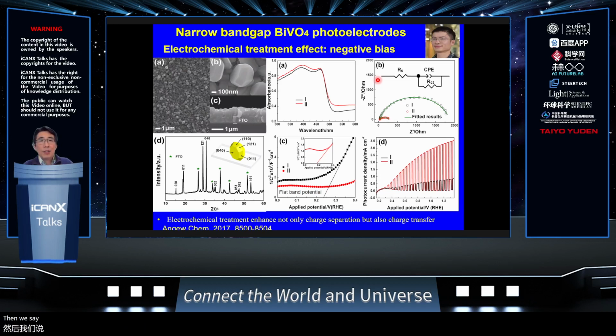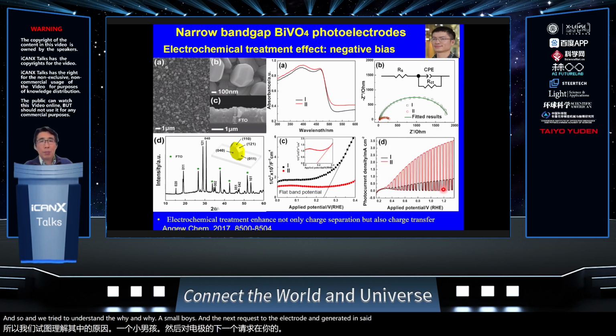Then we shifted our interest to narrow bandgap photoelectrodes, like bismuth vanadate. This is Dr. Wang's work, and he applied a very simple method, electrochemical treatment, onto the bismuth vanadate also produced by a hydrothermal process. Basically, a very small negative bias was applied for about 2.5 minutes, and the material showed a very significant increase in the photocurrent generated. We tried to understand why a small negative bias on the photoelectrode can generate such a big photocurrent improvement.